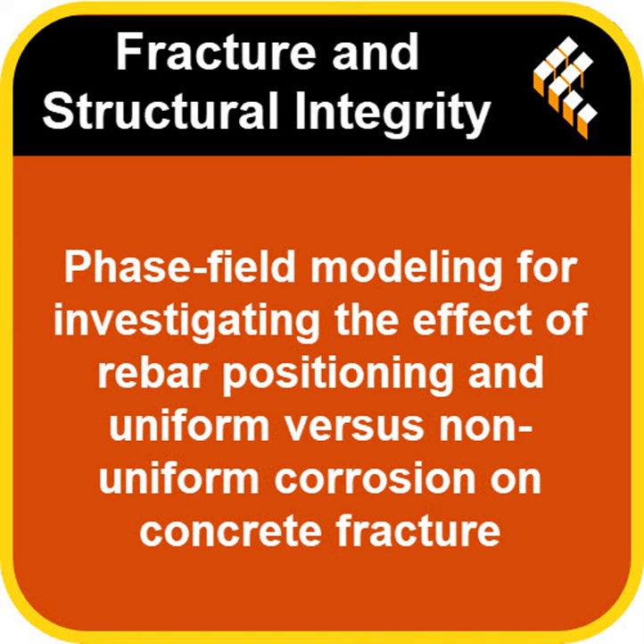Yeah, for the setups with multiple smaller rebars like the 2D14s or 3D12s, the amount of extra rust needed between T1 and T2, between initiation and propagation to the edge, is a growth phase. Right. That growth phase required less additional rust expansion for uniform corrosion. But for non-uniform, while it might have needed less rust right at T1, it needed a larger amount of additional rust to get to T2. So maybe slower to start, but then needs more push to fully break through. Something like that seems to be implied, yes.